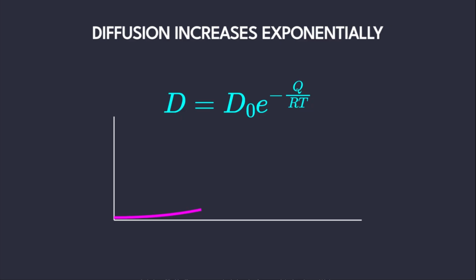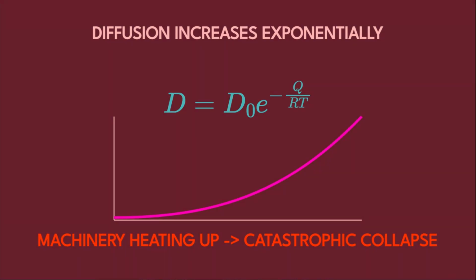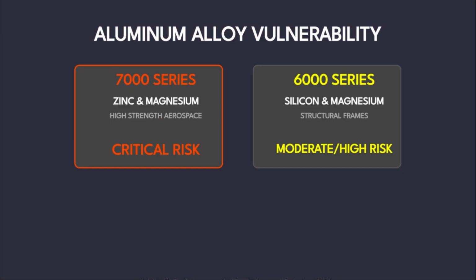Second, as the temperature increases, the kinetic energy of the atoms rises, accelerating the rate at which gallium atoms migrate through the grain boundaries. This relationship follows the Arrhenius equation, where the rate of diffusion increases exponentially with temperature. In industrial environments or high-friction zones where aluminum components operate at elevated temperatures, the presence of gallium is even more catastrophic. Even a trace amount of gallium that might be stable in a cool climate can suddenly become a liquid and cause a structural collapse if the machinery heats up during operation.